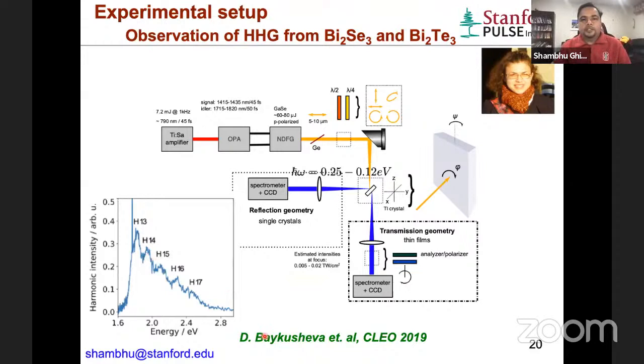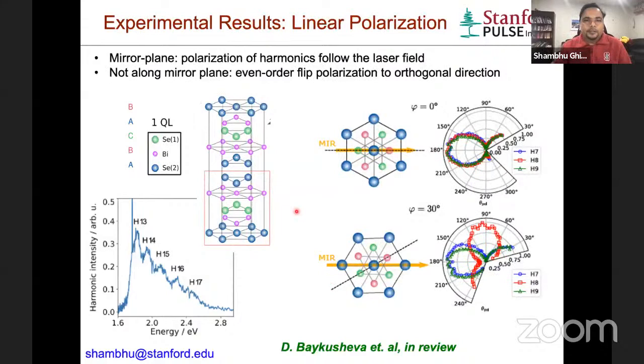The first set of results were published in CLEO 2019. These are detailed polarization analyses of harmonics. So let me run this through in more detail. This is the bismuth selenide crystal again with this crystal structure. This is a layered material that has bismuth and selenium as alternating layers. And this is one unit of the system called the quintuple layer, because it has five alternating layers. When you look at this system from the top, which is the surface, the surface does not have inversion symmetry in some orientations, and that becomes really useful.